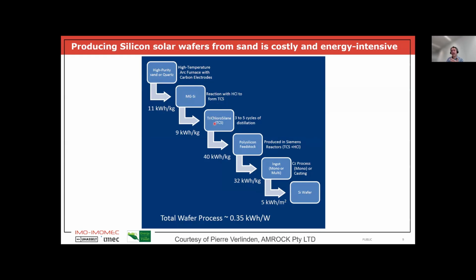So this is basically done in the gas phase by a kind of distillation. Then we have a very pure silicon gas. We have to go back to the solid state. So for this, we again need a high temperature reactor, very high temperature. So lots of energy needed to create a polysilicon. But then the polysilicon has to be remolten and reshaped into the ingot form. So again, you need to go to very high temperatures, above 1400 degrees, the melting point of silicon, to form the ingot. And then finally, we are wire sawing the ingot into individual silicon wafers, but we're also losing a little bit of silicon there because of the cutting process.